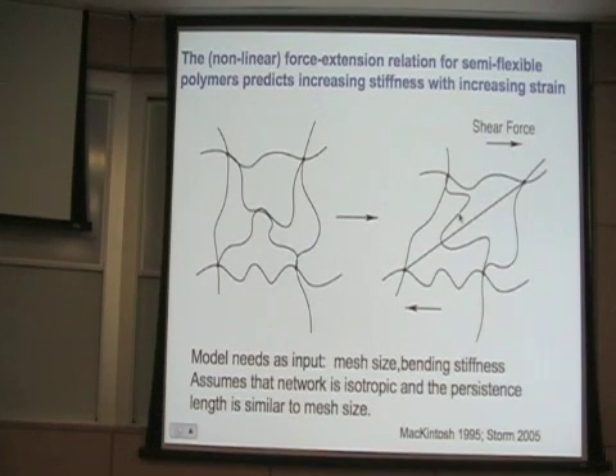people, and there are two really interesting models that can account for many of these aspects. One is that many of these polymers are very different from synthetic elastomers in that their persistence lengths are very large. The persistence lengths are on the order of the mesh size of the network, so hundreds of nanometers or a micron or so. And that means that the intrinsic force extension curve of the elastic elements inside that network, those force extension curves are intrinsically nonlinear. So by putting a shear, any kind of deformation on these networks, it takes much more force to stretch a filament than it does to compress it, and that gives rise to nonlinearity in the elastic modulus.